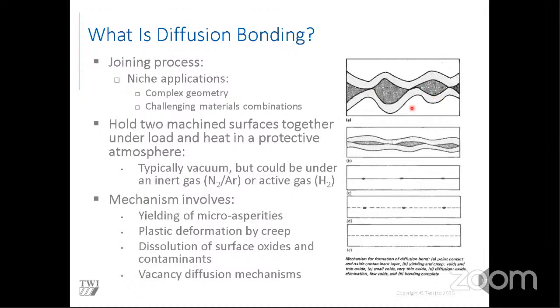So the first thing that happens when you're applying the load and the heat is these micro asperities begin to deform. Then you start to get plastic deformation processes take over, sort of creep type processes. Most materials will have an oxide layer on the outside, and at the temperature of diffusion bonding, these will then begin to diffuse into the parent material.